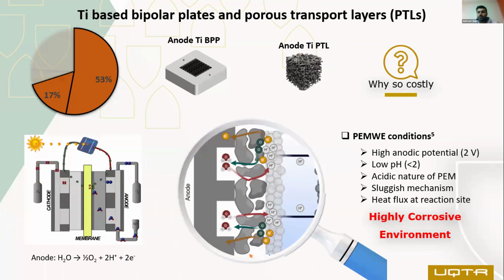Almost 70% of cost goes to these two titanium-based components. One is the bipolar plates and the second one is the titanium-based porous transport layers. And why are these components so costly? Because if we see the operating conditions at the anode side of the PEM water electrolyzer cell, it has high anodic potential, a low pH, acidic nature of proton exchange membrane, and heat flux at reaction sites. This environment is perfectly harsh to corrode the metallic components during long-term operations. That's why we have to use titanium-based bipolar plates and PTLs, because titanium is a highly stable metal under acidic operating conditions. But titanium also comes with some serious limitations.